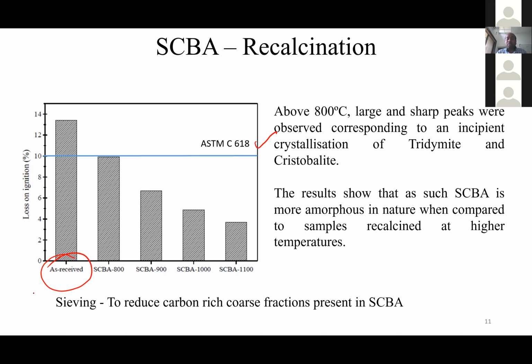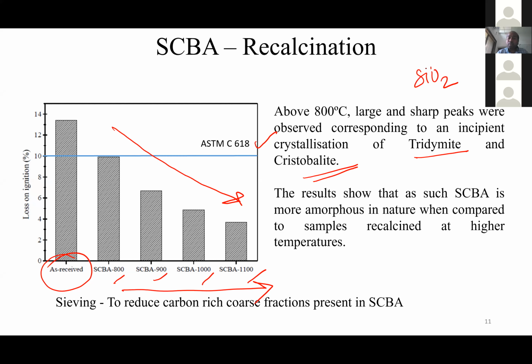So what we have done is we have tried to incinerate the materials at different temperatures, 800, 900, 1000, 1100, to see whether we could reduce the carbon fractions. Of course, based on the study, it is very evident that the carbon percentage, LOI, decreases with increase in temperature. But the problem is, once we start to increase the temperature, crystallinity creeps in. Tridymite and cristobalite, these are also SiO2. Okay, these are crystalline materials, which means they will not possess reactive potential.